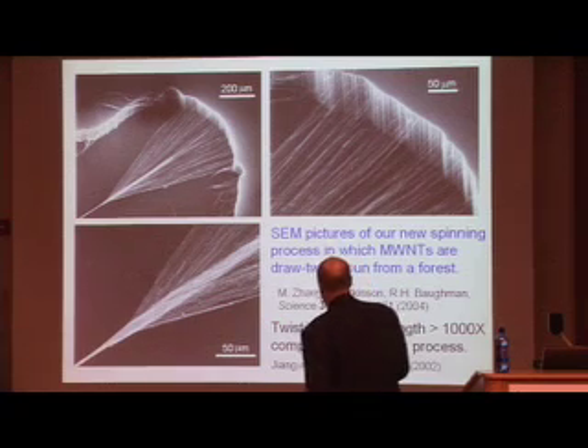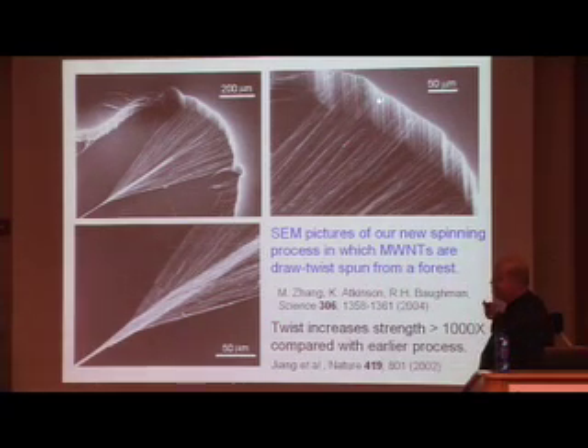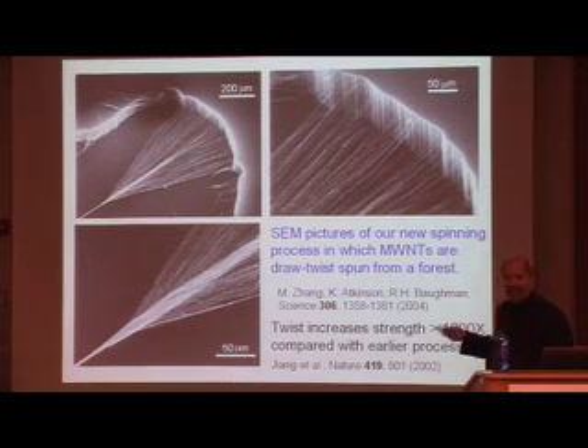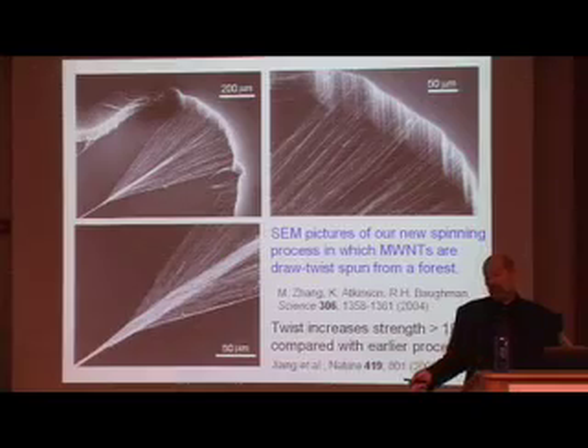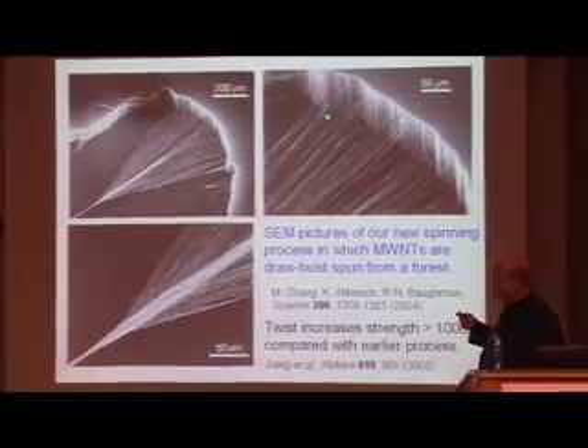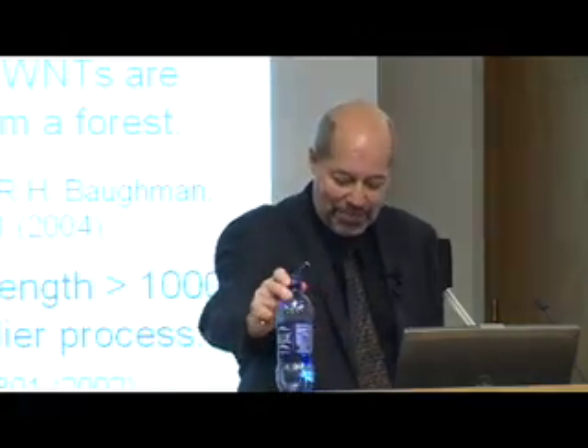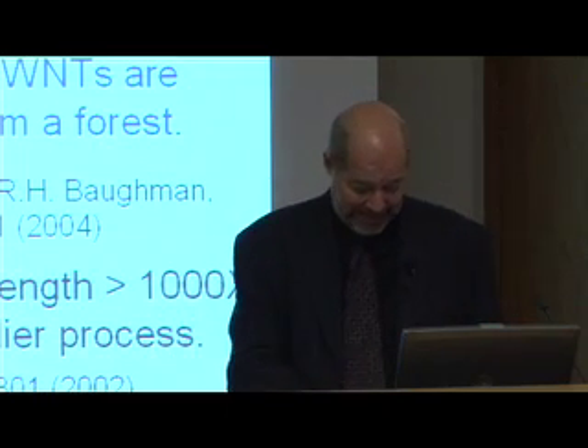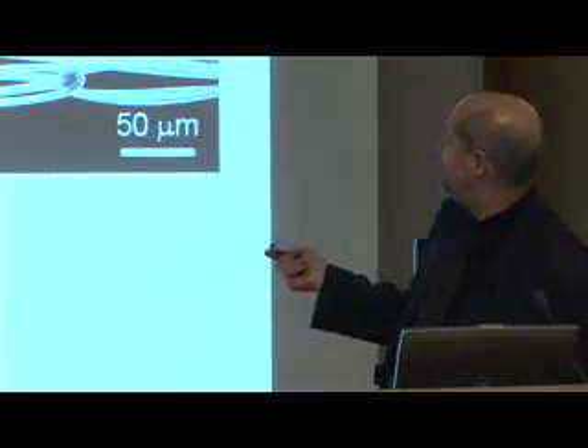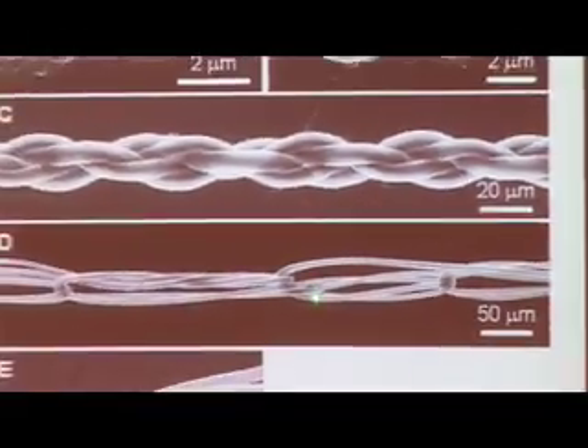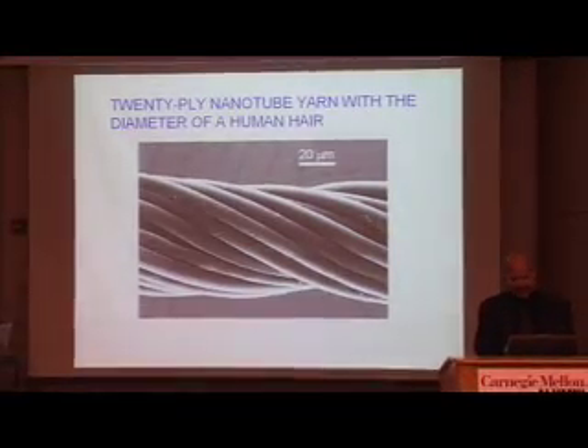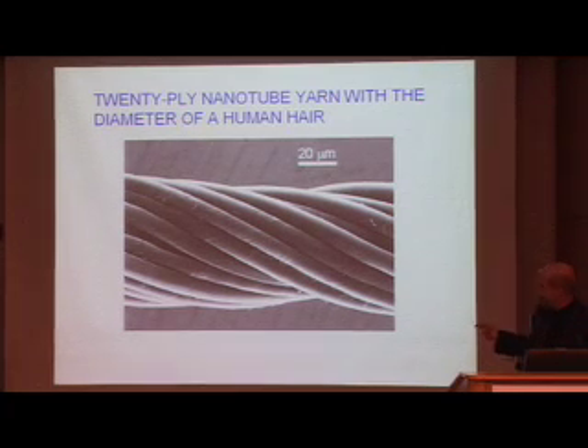Now, Chinese researchers had discovered that you could pull a yarn from the side of a nanotube forest. But the yarn strength was extremely low, not usable. We discovered if we just deployed an ancient technology of twist-based spinning, basically deployed this twist-based spinning on the nanoscale, that we can increase mechanical properties by a factor of about 1,000. And as a result, we're able to make singles yarn, 2-ply yarn, 4-ply, knitted yarn, knotted yarn. We can make a 20-ply yarn with the diameter of a human hair.